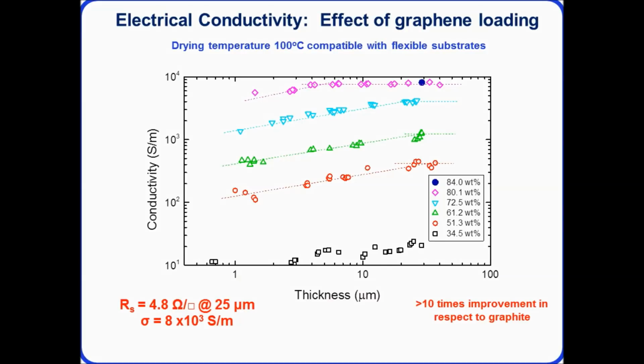And the best sheet resistance we can achieve with these films is around 5 ohms per square. So what we're doing here is just drying, removing the water at 100 degrees Celsius. We're not doing any further annealing. So this is something which is compatible with most plastic substrates and paper substrates. And so we demonstrate more than 10 times improvement in performance compared to the graphitic starting material.